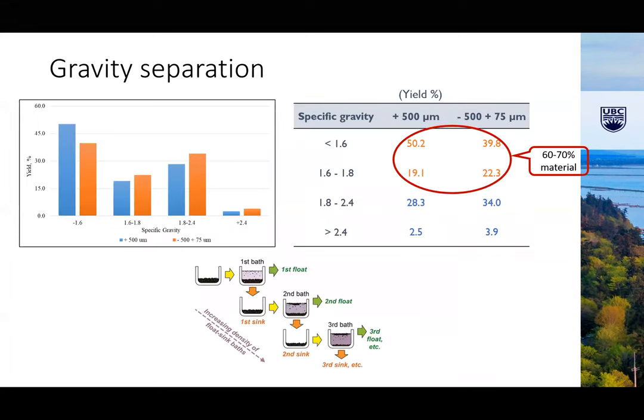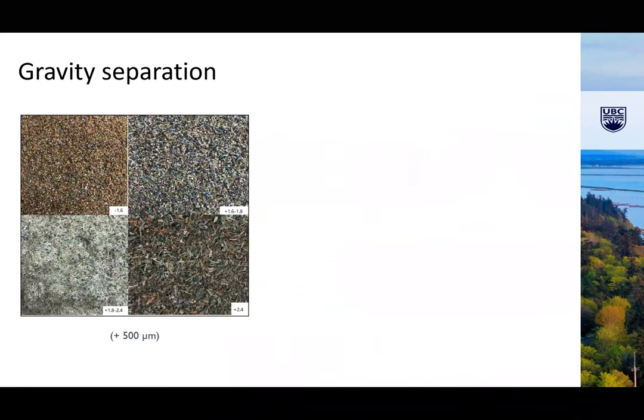So when the gravity separation was done, we looked at the top size of the material after shredder and hammer mill, which was 1 millimeter, and the material for this analysis was split into two fractions, plus 500 and minus 500 to 75 microns. So as you can see, 60 to 70% of material already was distributed into the lighter fractions. So that makes sense, because that's how much of the plastic resins we expected.